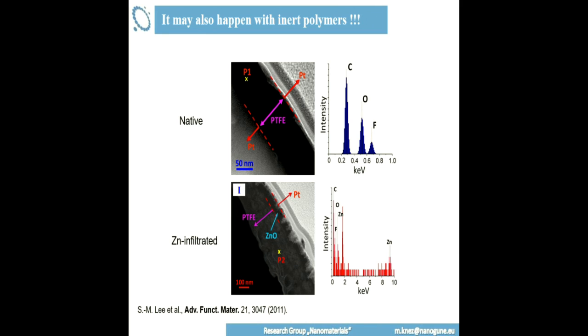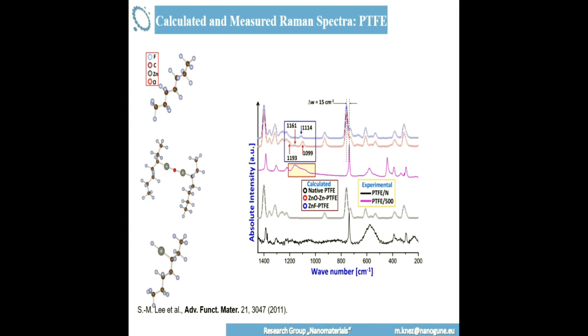You can also infiltrate Teflon. So be aware, even inert chemical substrates like Teflon, where you consider this is not going to react at all. Zinc oxide is able to modify, to make Teflon brittle, even at 70 degrees C. It's going to infiltrate, it's going to modify the chains of the polymer. What's happening there, we did some spectroscopy and some modeling here, DFT modeling. These zinc oxide